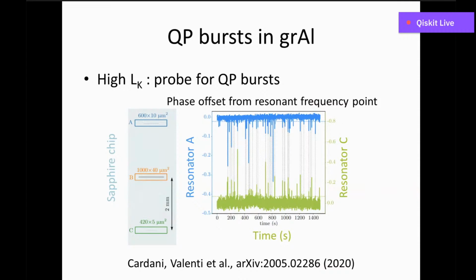Since these bursts are mediated by phonons that propagate in the substrate, then if I show my 3 resonators here sitting on the sapphire chip, phonons will reach resonators at the same time or very close in time, and this will be a source of time-correlated quasiparticle bursts, then time-correlated drops in resonant frequency in these resonators.